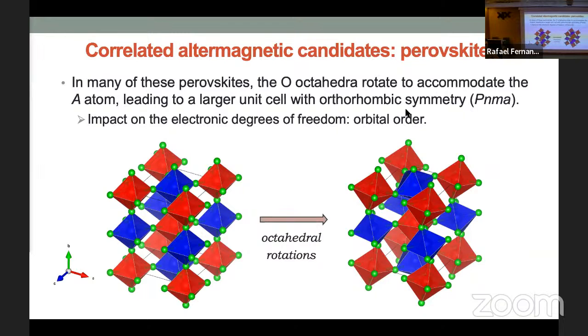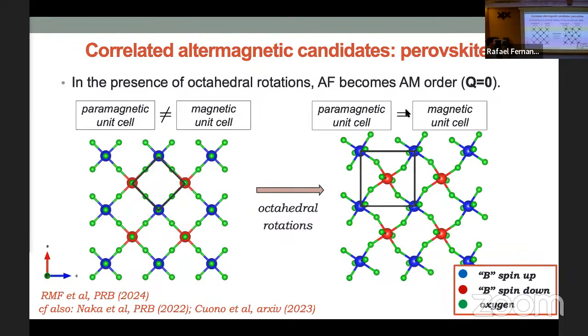This sounds a lot like what we discussed before, where you have a magnetic atom in a different environment. The difference here is that the magnetism is coming from a Mott insulating state. And in a lot of the perovskites, you can, to some extent, control the size of these octahedral distortions, for example in the rare earth titanates, by the size of your rare earth, by applying pressure, or by applying strain. So that offers an interesting possibility here, okay?